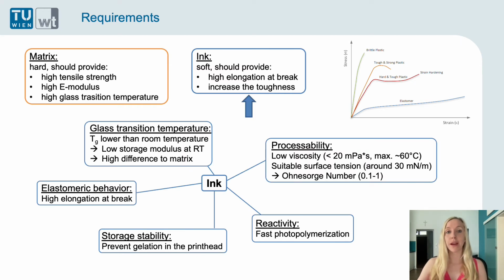And here are the requirements of the ink in detail. So we want to have a glass transition temperature lower than room temperature, because then we have a low storage modulus at room temperature and a high difference to the matrix material. As I already said, also the elongation at break should be high. Of course, it should be stable in storage to prevent gelation of the ink in the printhead.